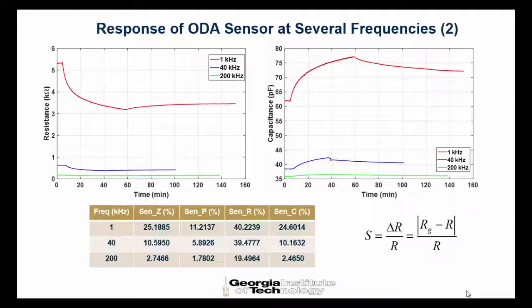So this table summarizes the frequency effect. You can see that most of the sensitivities are higher at 1 kilohertz and the lowest at 200 kilohertz, whether it's the magnitude of the impedance or phase of the impedance or the equivalent resistance or capacitance. And this is the sensitivity calculation.